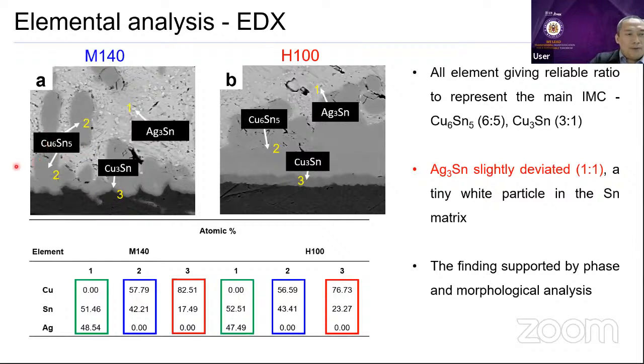Normally, when we run reflow, we can get Cu6Sn5. Cu6Sn5 can be at the interface and inside the bulk of the solder, right? And this is enough for the joining. At the same time, sometimes we can have Ag3Sn, which is the powder here. But when we run this microwave, luckily we can see that there is another thin small layer. Maybe we can see this one, guys. All right, we can see this one.